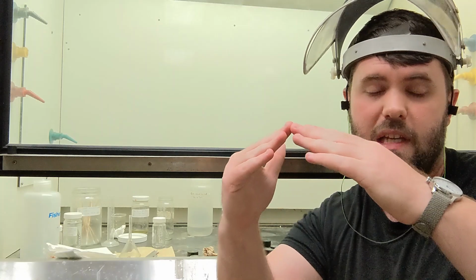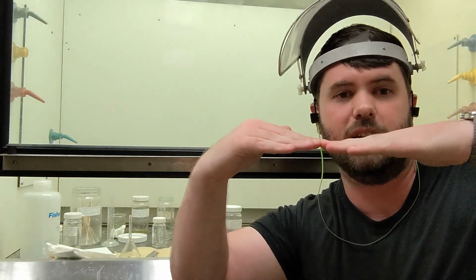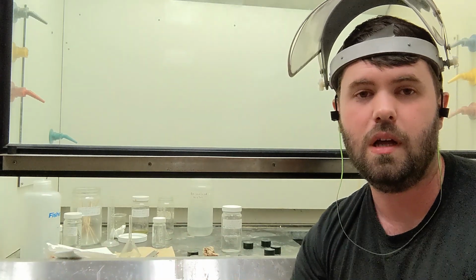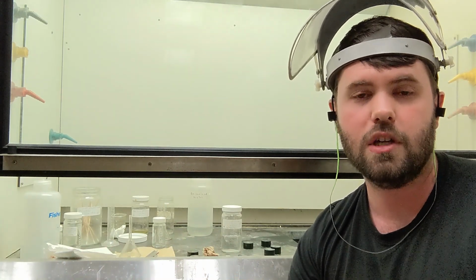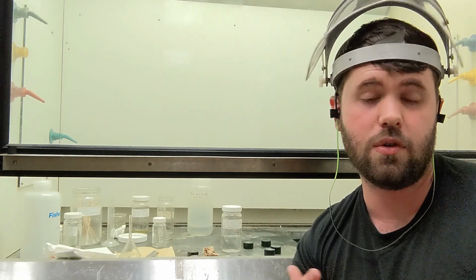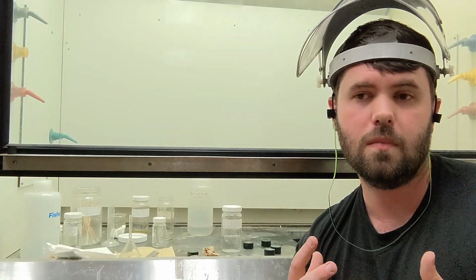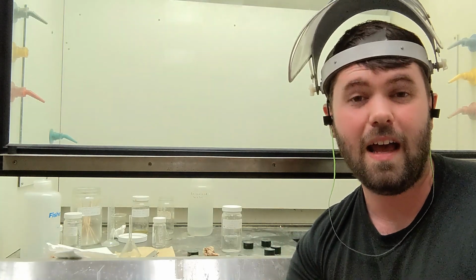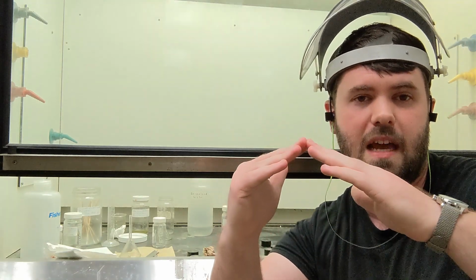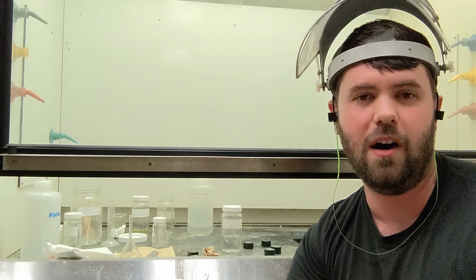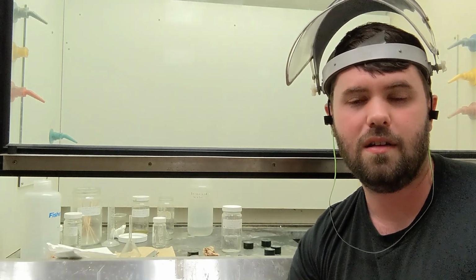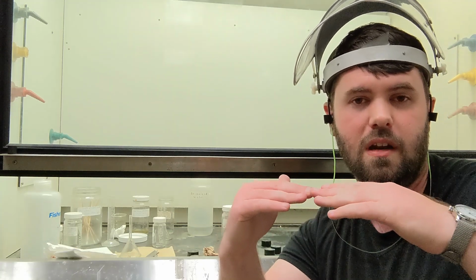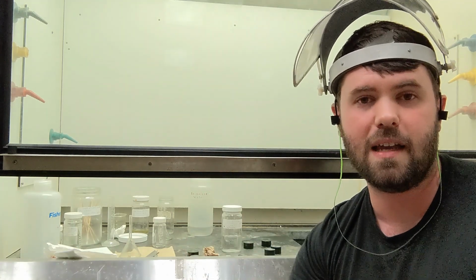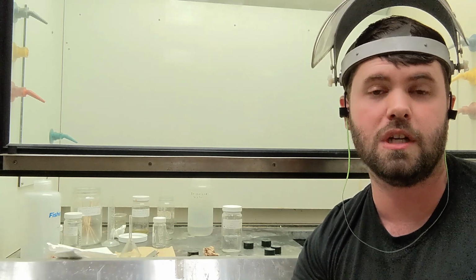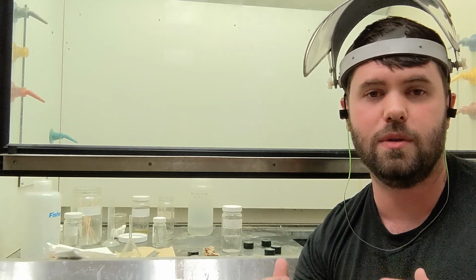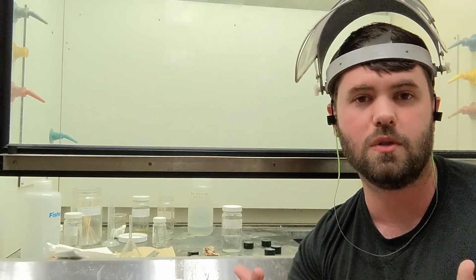And the reason they do this is to relieve stress, because to maintain a perfect crystalline lattice, a perfect line throughout the entire sample is actually really difficult, because the sample is not truly uniform. So they have these grains, and at grain boundaries, stress is relieved, and these atoms meet. The thing is, also, at grain boundaries, because these atoms are slightly offset, because they have this angle, they are not at the perfect orientation for bonding. That means their bonds are slightly weaker than inside the grain, inside of a perfect crystalline ordered structure. And that means if you attack it with a caustic etchant, caustic solution that eats away at these boundaries, they're going to attack the atoms at the grain boundaries first, because they are the most weakly bonded.